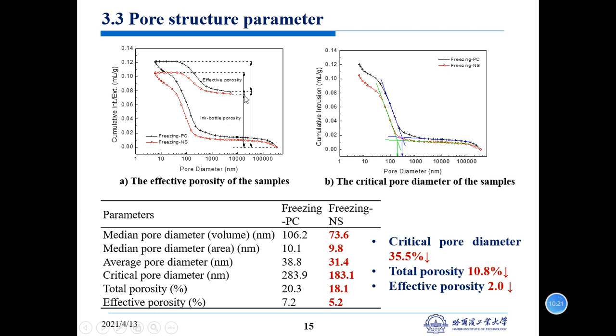And we can also see the other pore structure parameters are also decreased, like in this table. We can see the critical pore diameter decreased by up to 35.5%, and total porosity decreased by 10.8%.